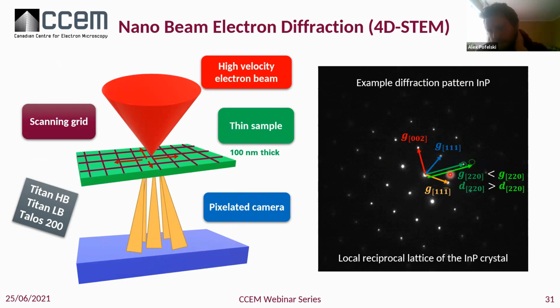So here we have the diffraction recording in the indium phosphide, zinc blende type of structure. And so you can identify the peaks. We can also index them. And how we look at the strain in this type of structure is to look at the variation of the G vectors. So this is just an example here. You have the G220 here.